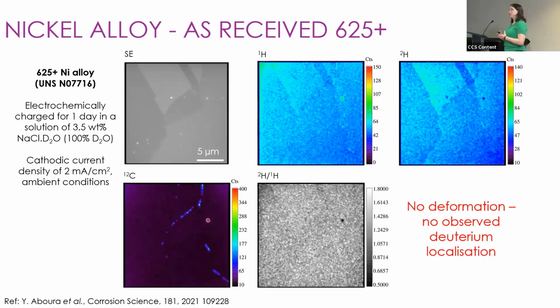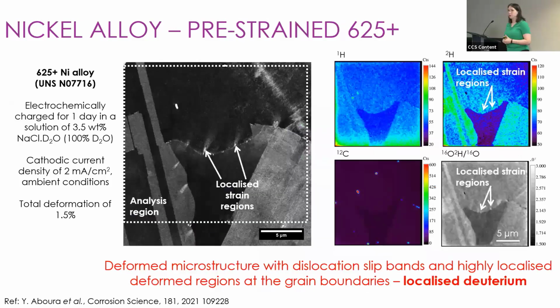So the next thing to do was to increase the complexity of this experiment and look at a pre-strained sample of 625 plus. We're now introducing some strain into our sample. We had a total deformation of 1.5%. And you can see from the backscattered electron image that we took just before we loaded this sample into the NanoSIMS, there are these clear localized strain regions around this grain boundary.